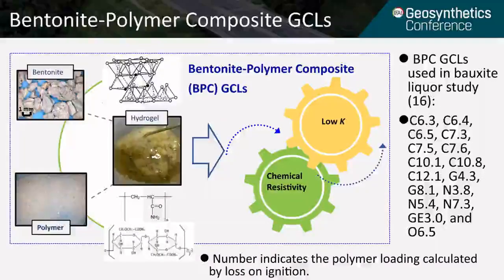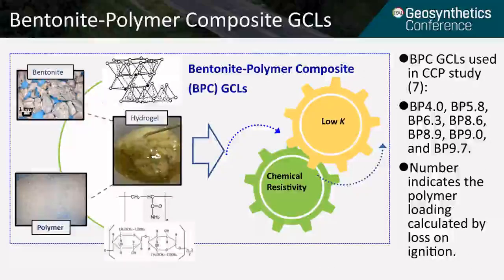The BPC GCL is designed to improve the chemical resistance and reduce the hydraulic conductivity of sodium bentonite. In this study, we evaluated 16 BPC GCLs for bauxite liquors. The number indicates the polymer loading of these GCLs, which is measured by the loss on ignition method created by Dr. Scalia in 2014. Similarly, for the CCP studies, we used 7 BPC GCLs, and the number also indicates the polymer loading. Besides these GCLs, we also tested sodium bentonite for both bauxite liquor and CCP leachates.